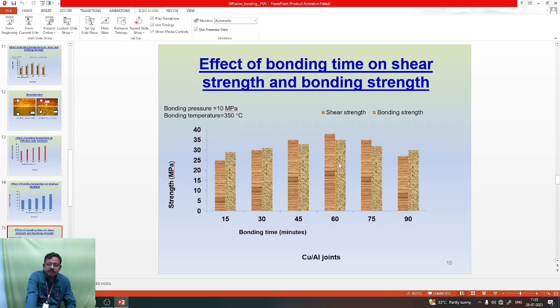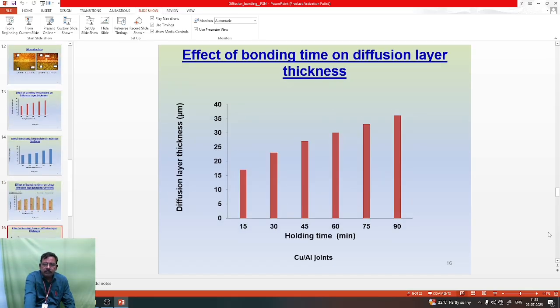Because here at 60 minutes, the shear strength and bonding strength are higher, since the diffusion layer thickness is optimum. At this optimum diffusion layer thickness, we can get the higher shear strength and bonding strength. The effect of bonding time on diffusion layer thickness. The diffusion layer thickness depends upon the holding time. Here at 15 minutes, the diffusion layer thickness is less. And at 30 minutes, the diffusion layer thickness linearly increased. So the diffusion layer thickness depends upon the bonding time. Whenever the bonding time increases, the diffusion layer thickness also increases.